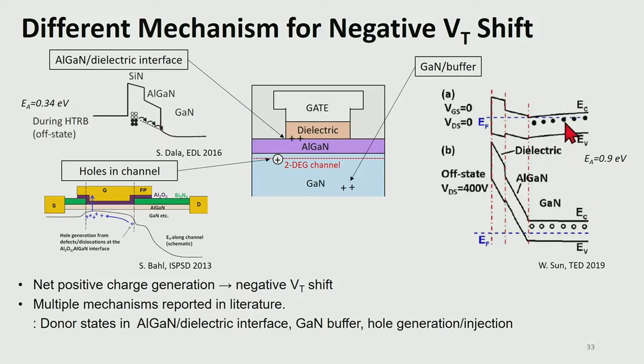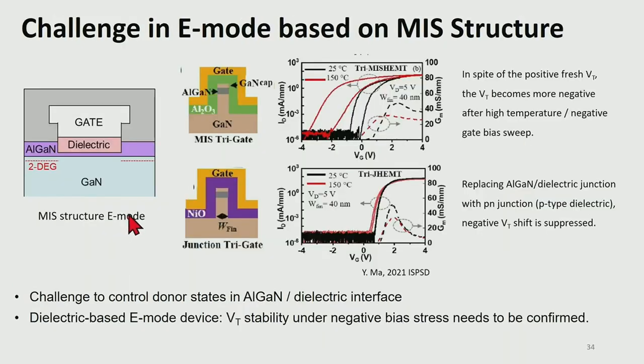Another explanation is also related to donor states, but the location is not the AlGaN-dielectric interface, but in the gallium nitride channel or in the back barrier region. But similar to the surface donor states, once these donor states in the GaN channel are activated, they provide a fixed positive charge effect, which causes a negative VT shift. Lastly, the holes generated under high drain voltage stress can flow into the channel area following the electric field and get injected into the gate area and cause a negative VT shift. And this negative VT shift is one of the key reasons why it's very challenging to make a stable enhancement mode operation with a gate dielectric.